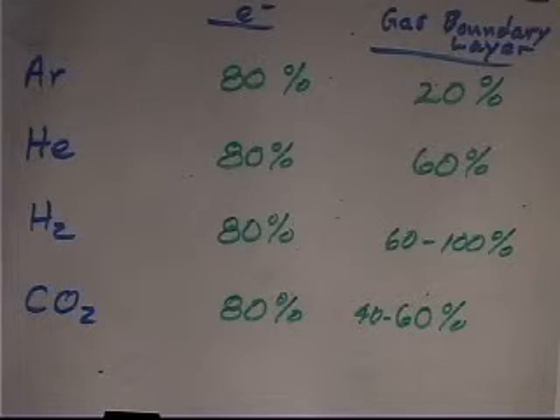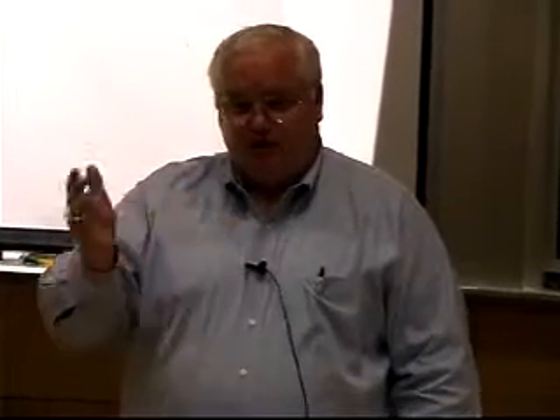Except that's not true. In fact, the certified welding engineering exam has that same question on it, and the official answer asks you to use these differences in ionization energy to explain why helium's a hotter arc. It's wrong. If you actually measure a helium arc on a molten weld pool and an argon arc on a molten weld pool, because they both have the same metal vapor, the temperatures of the plasma are essentially the same.